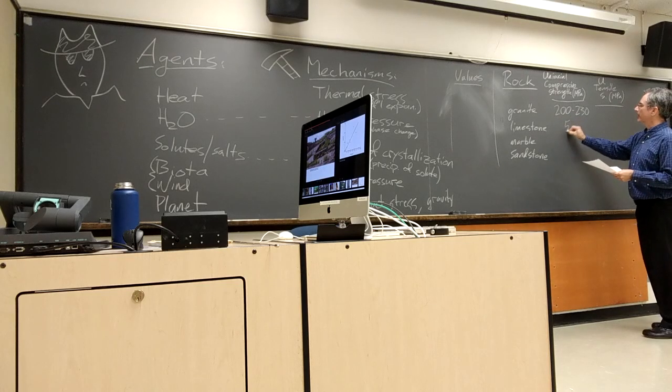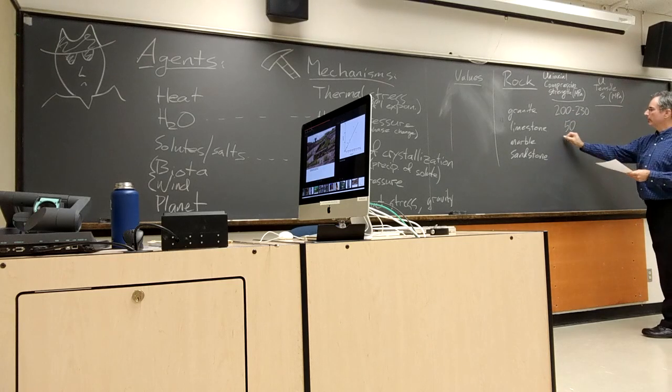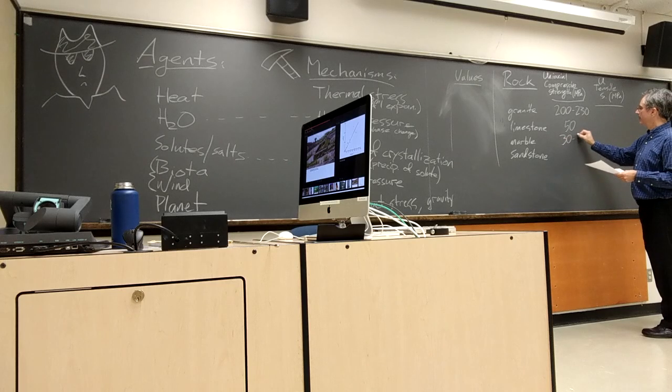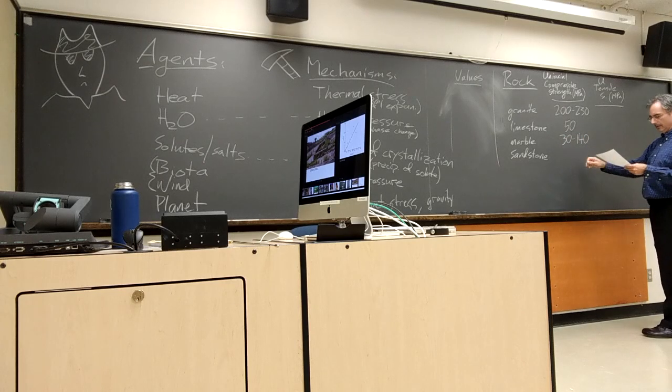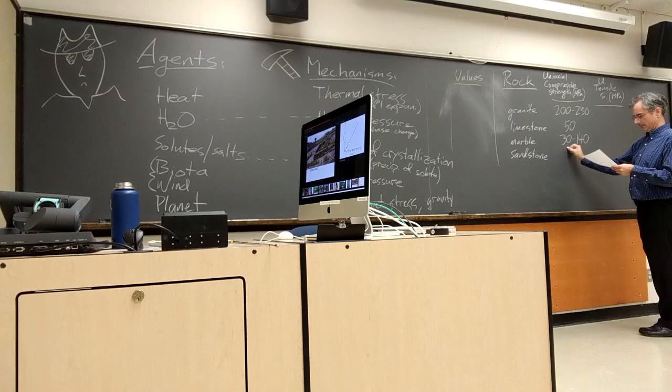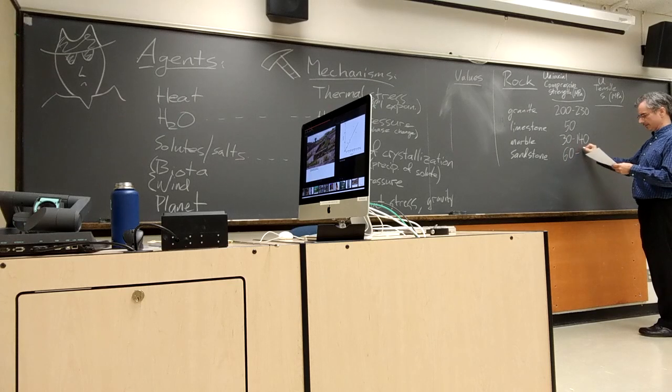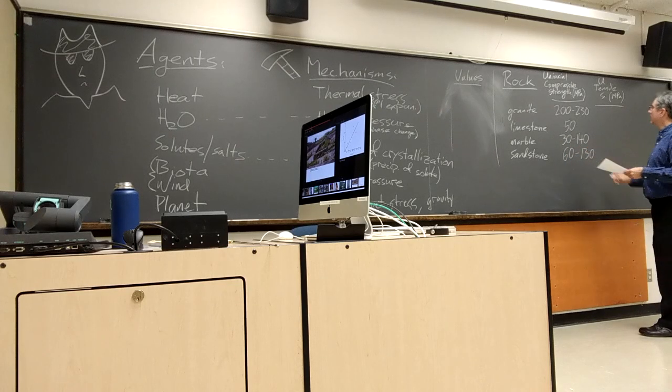Limestone, something like 50. Marble, bigger range, 30 to 140. And sandstone, also a relatively large range, 60 to 130. But the tensile strengths are quite a bit lower. For granite, 13 megapascals. Limestone, 3 to 4. Marble, 5 to 8. And sandstone, 3 to 7.